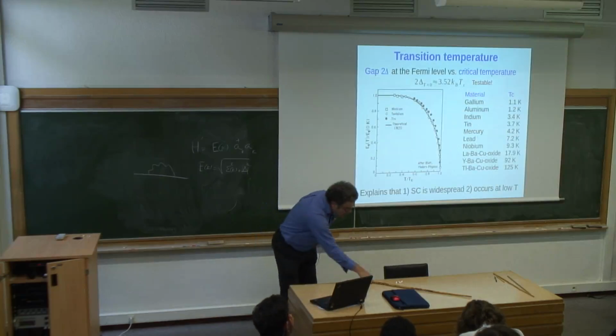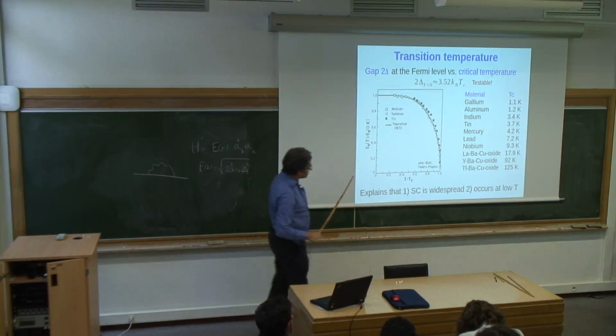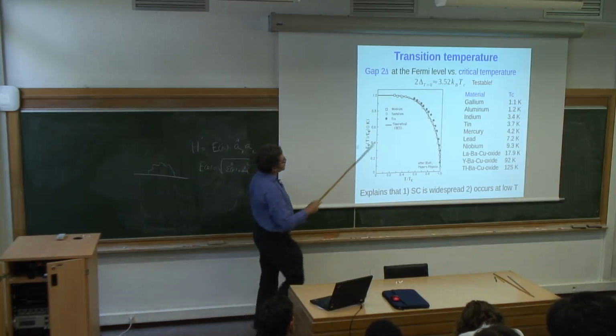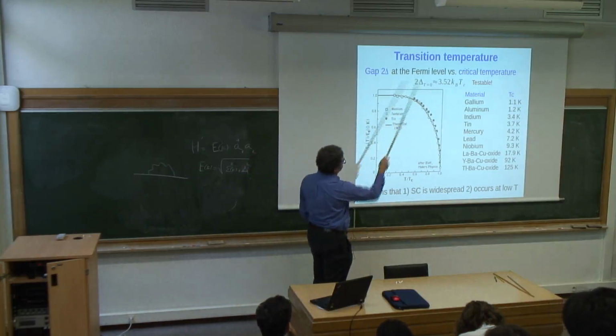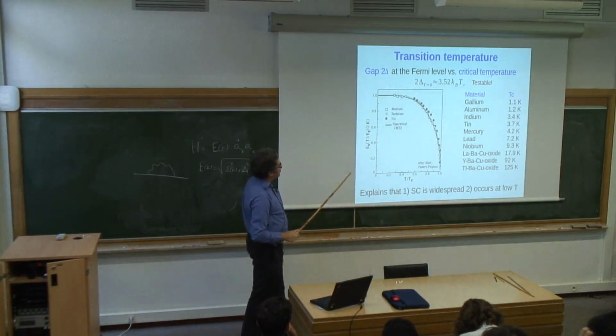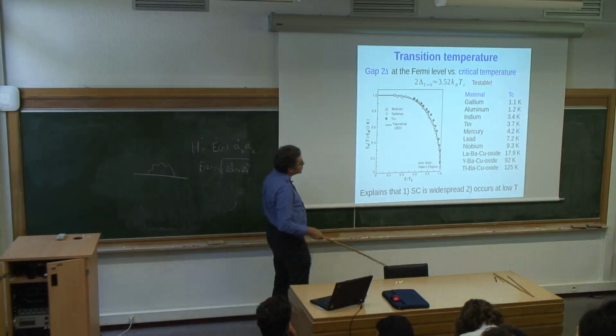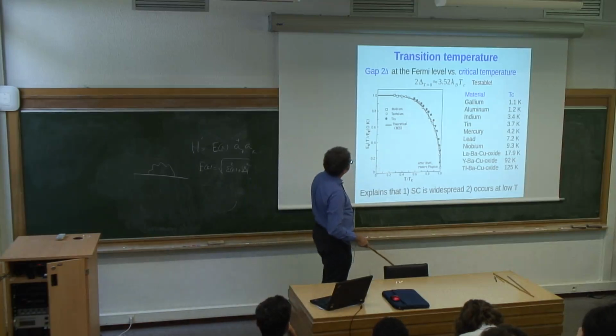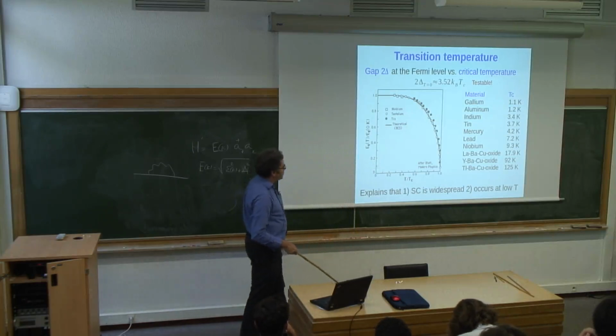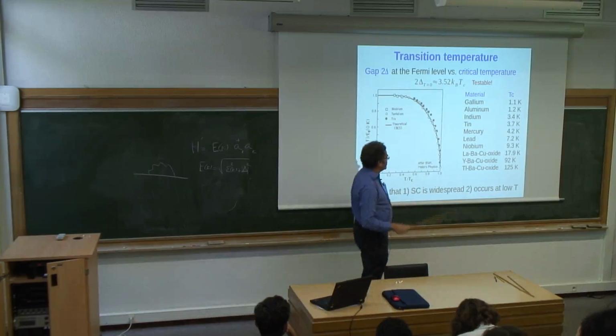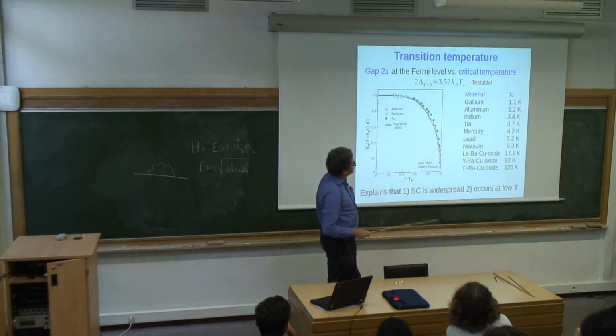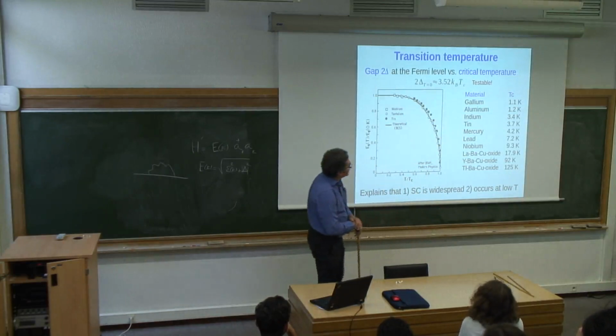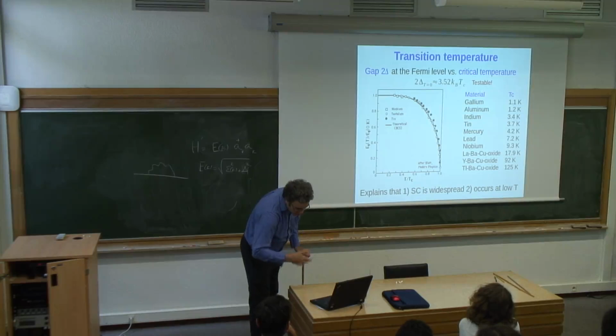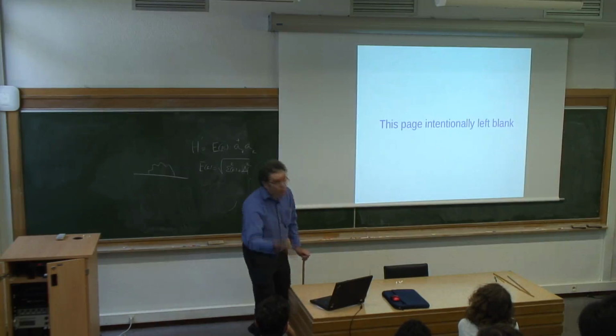So that's where all this comes from. And so this relation between energy gap and critical temperature is testable, and was one of the first experiments that confirmed BCS theory predictions, and it works surprisingly well even in the materials where people expect strong deviations from the BCS pairing mechanism. But by order of magnitude, it should be true, and it does. Right? So that's the end of the generic part.